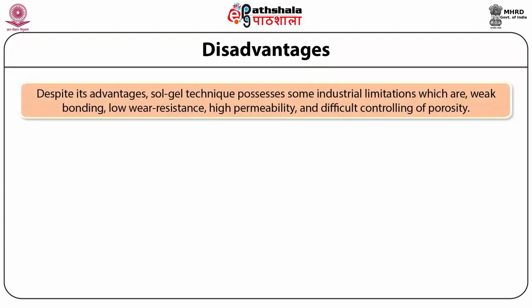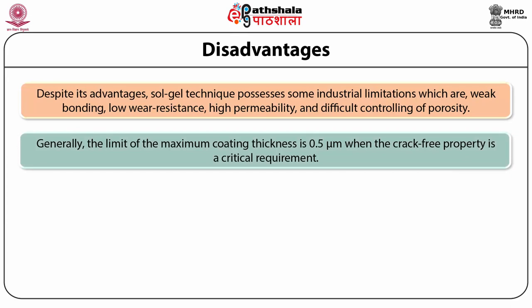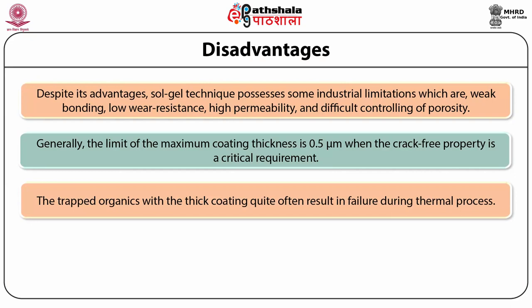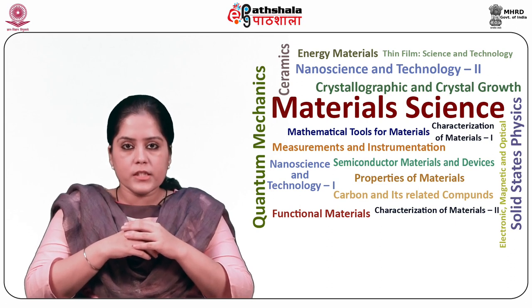Despite its advantages, the sol-gel technique has some industrial limitations: weak bonding, low wear resistance, high permeability, and difficulty in controlling porosity. Generally, the limit of the maximum coating thickness is 0.5 micron when crack-free property is a critical requirement. Also, trapped organics within the thick coating quite often result in failure during thermal processing.